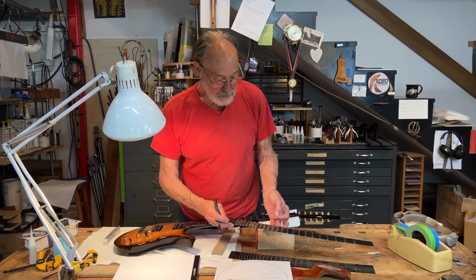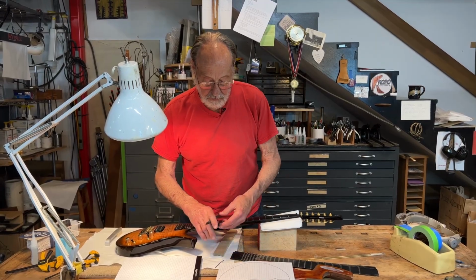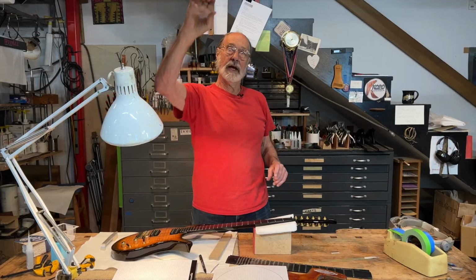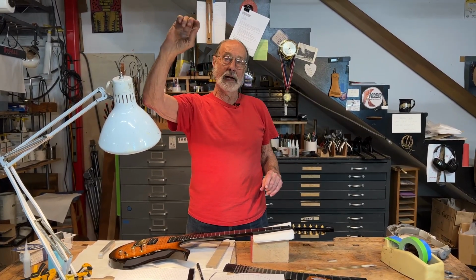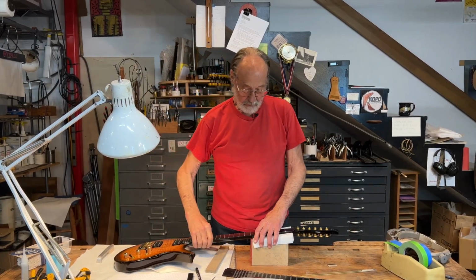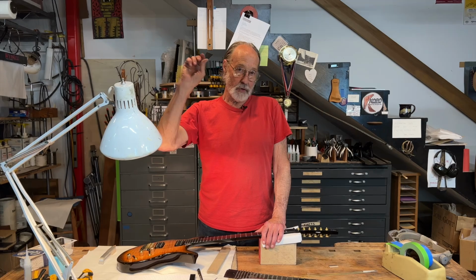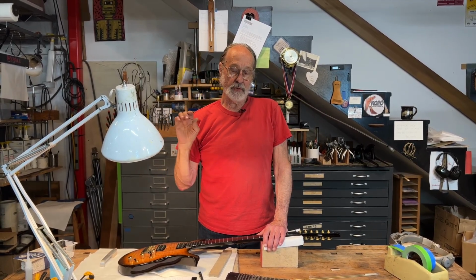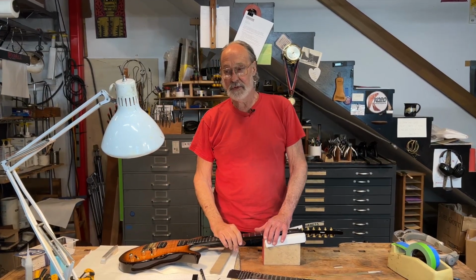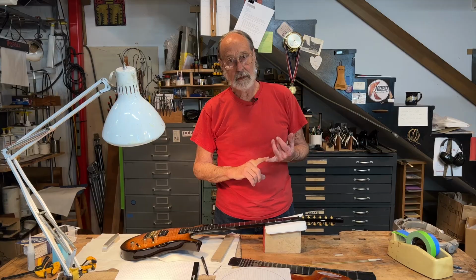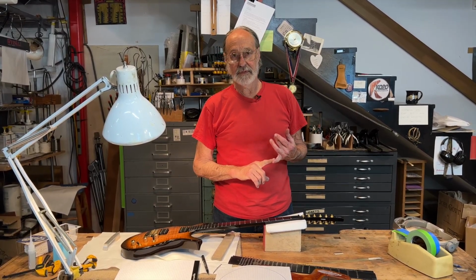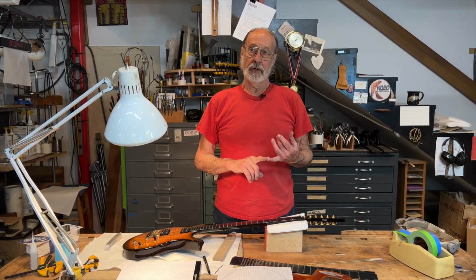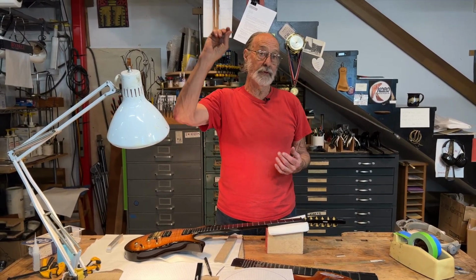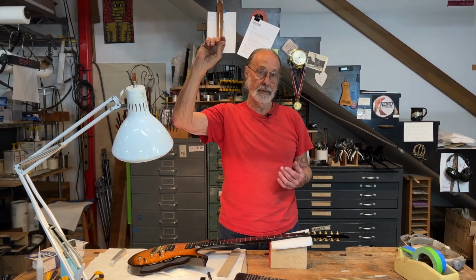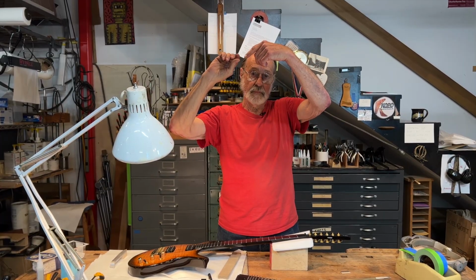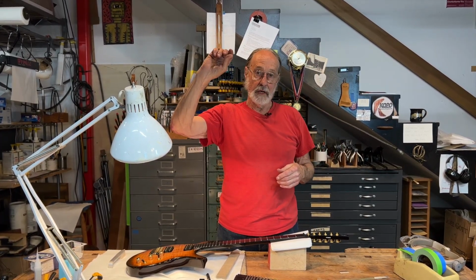And so we ended up using an acrylic adhesive, and those of you who remember rear view mirrors in your car that were attached to a little glob of metal glued right onto the glass, they don't do this anymore, but when we were young, they did. And that acrylic adhesive was used for that job. The kind that we used was a medical adhesive made by the Dymax company, and it was called Multicure because you could cure it with heat, about 125C or 250F roughly, or you could cure it with ultraviolet light, like they did when they put that little block of steel on the inside of a car windshield. The sunlight would hit the adhesive and it would kick the adhesive coming through the glass.